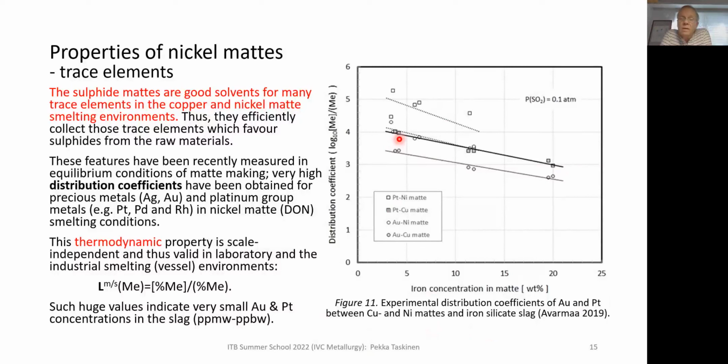So that means that the chemical dissolution of platinum is almost negligible in slag when we are in equilibrium conditions.